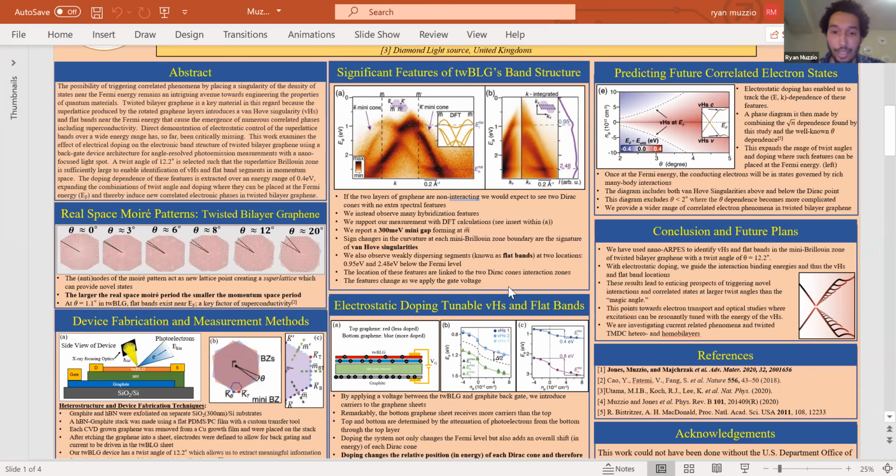And the interesting thing is that not only do we just have 2 pieces of graphene sitting here, but we actually are able to probe them electrically. So we can drive current and we can apply a gate. And so when we apply the gate, what we notice is that the top layer of graphene, or twisted bilayer graphene, receives less electrons than the bottom layer, thus shifting the Dirac cones with respect to each other. That shifting, in turn, will then change the location of the flat band as well as the Van Hove singularity.